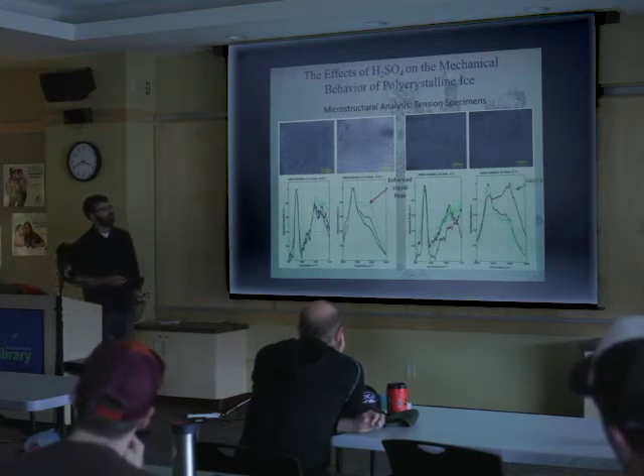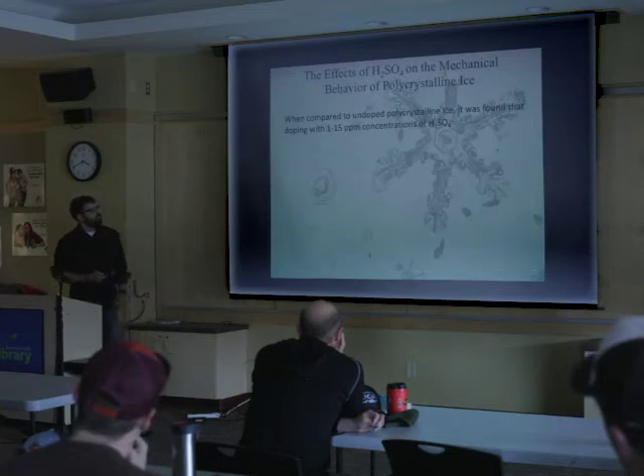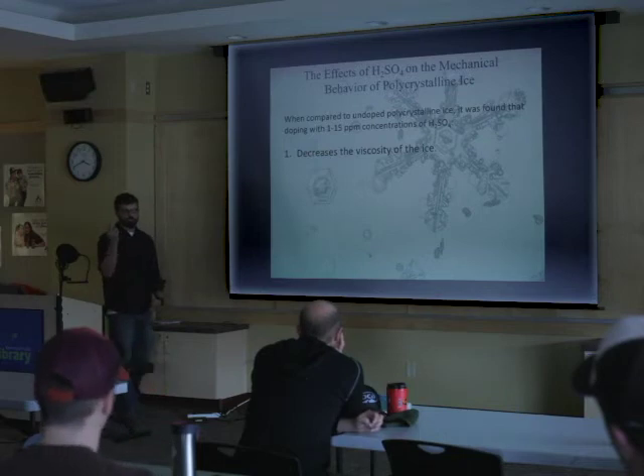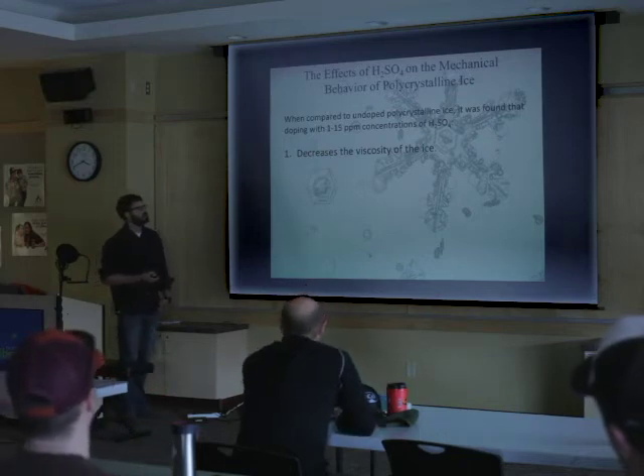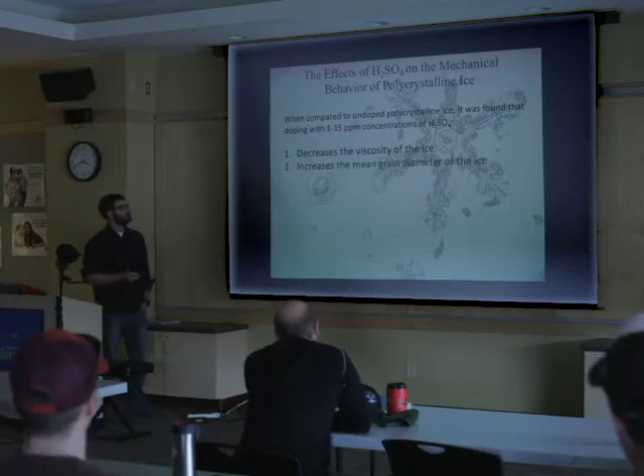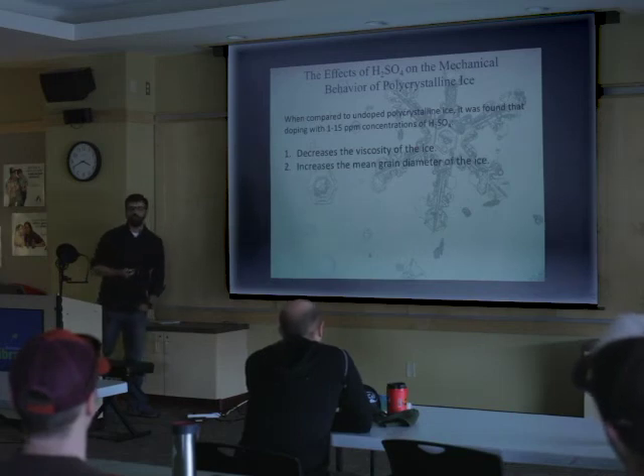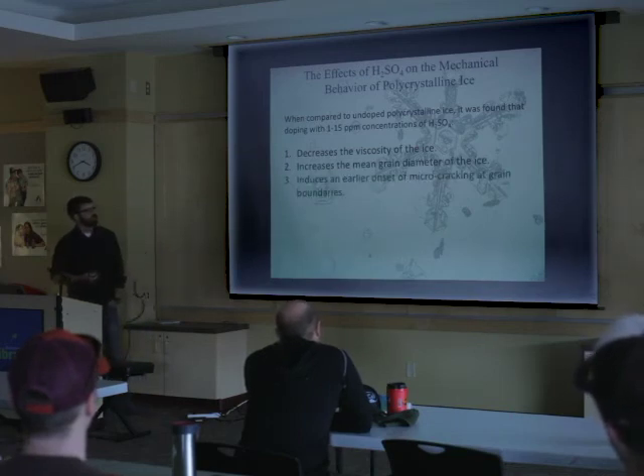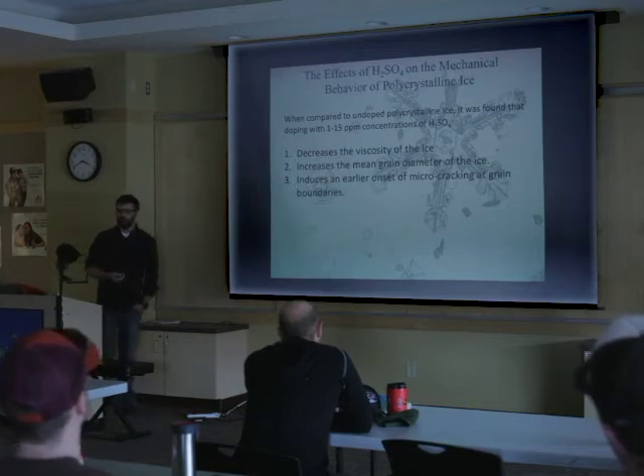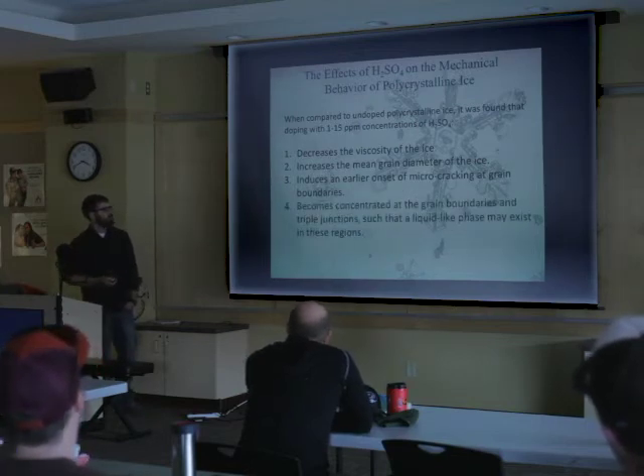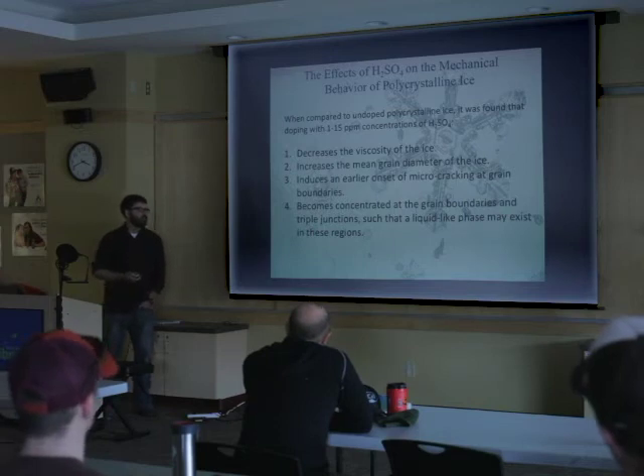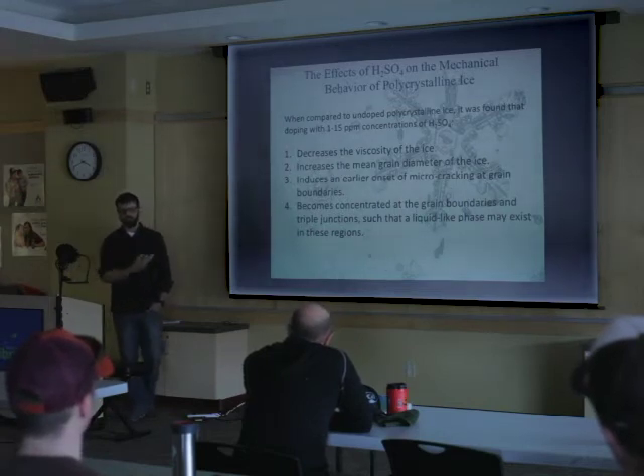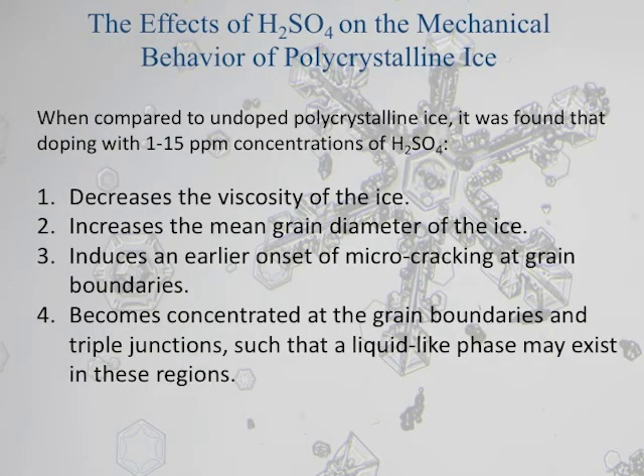So to conclude, what did we learn from this study? Just this little bit of sulfuric acid, which comes from natural rainwater and snow, decreases the viscosity of natural ice. It increases the mean grain diameter of the ice. I think we saw that. It induces an earlier onset of microcracking at the grain boundaries. That was pretty clear. And it becomes concentrated at the grain boundaries and triple junctions such that a liquid-like phase exists in those regions. We were able to show that with the Raman spectroscopy.